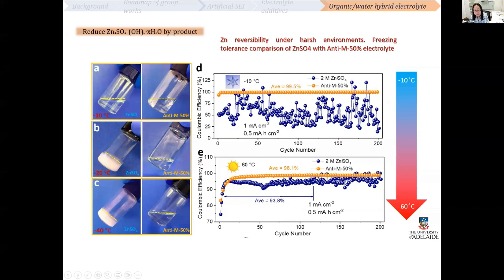And the very amazing thing is this hybrid electrolyte improves the low temperature and high temperature performance as well. You can see the bare electrolyte is frozen at -20 degrees, but the hybrid electrolyte, even at -40 degrees, still keeps a liquid state. And you can see at -10 degrees, the zinc copper asymmetric cell has a coulombic efficiency of 99.5%, which is very promising. At 60 degrees, the reversibility is also better than the baseline electrolyte.